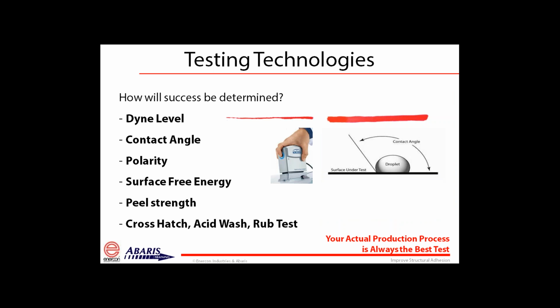So Lou did a great job of talking about how you can test the materials. As I get into some details here, I just want to cover those again. Dyne level is one. It's a very simple, easy way to test surface energy. It is not always the best indicator. Sometimes you'll see a high dyne level where you don't get treatment, or a low dyne level where you do get good adhesion. Contact angle steps that up. Measuring the surface free energy and polarity on the surface is another advanced way that we talked about. Ultimately, you're going to look at the peel strength or some other sort of test that you're going to apply after whatever you're bonding to the surface as well.